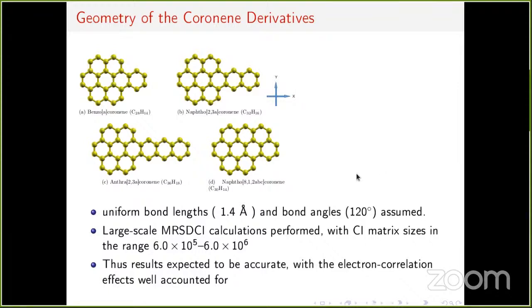Okay, so in our calculations, we assumed uniform bond lengths, which is just fine for semi-empirical calculations, and also uniform bond angles of 120 degrees. And we performed large-scale multi-reference singles and doubles CI calculations with CI matrix sizes ranging from 600,000 to 6 million. So this is a fairly large scale calculation, so we expect our results to be fairly accurate and with the electron correlation effects well accounted for.